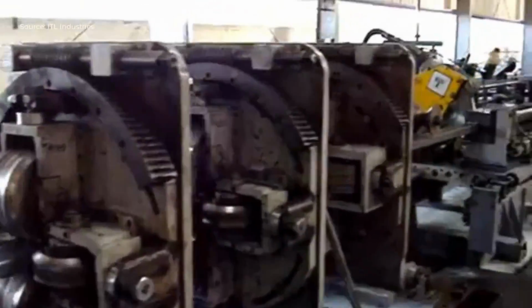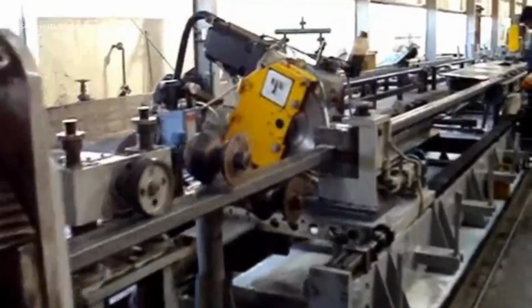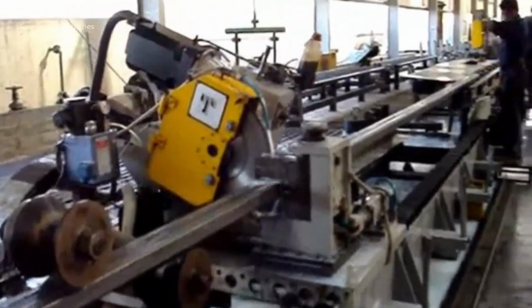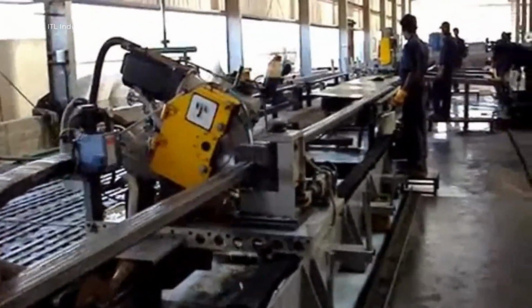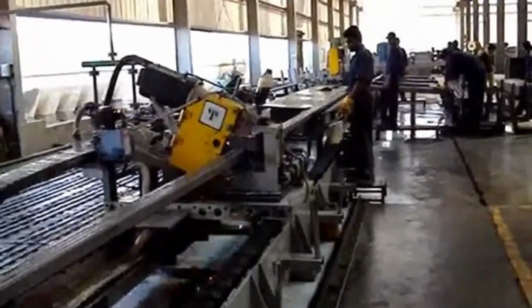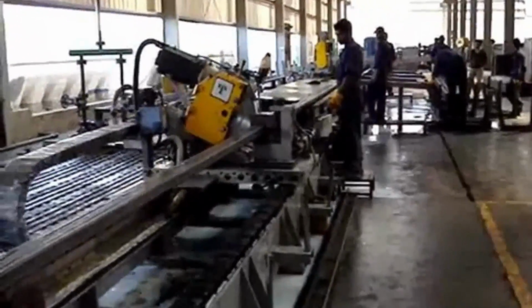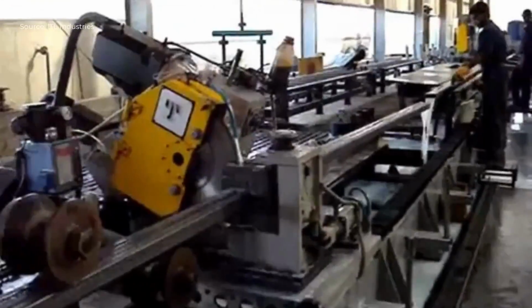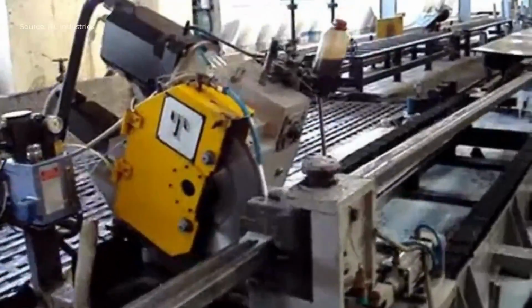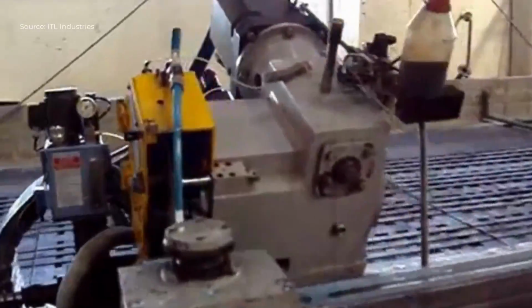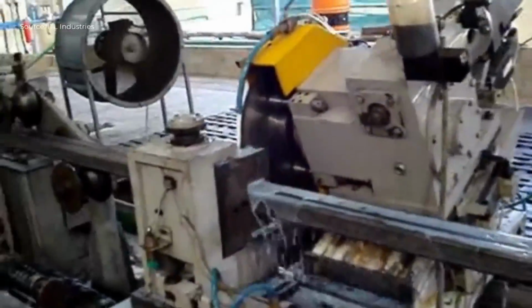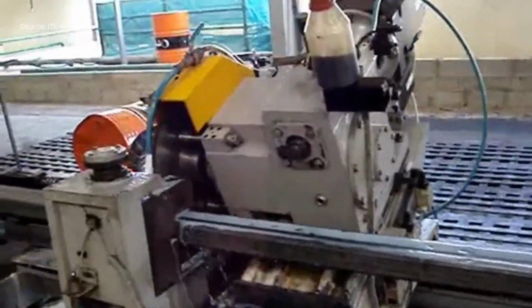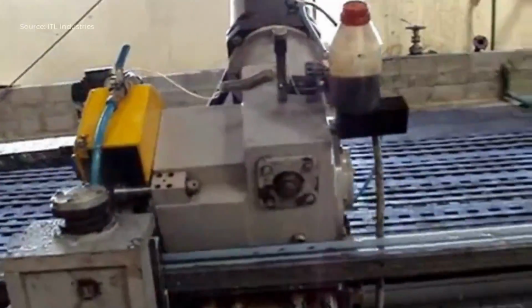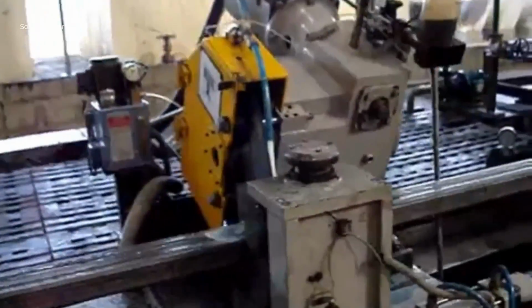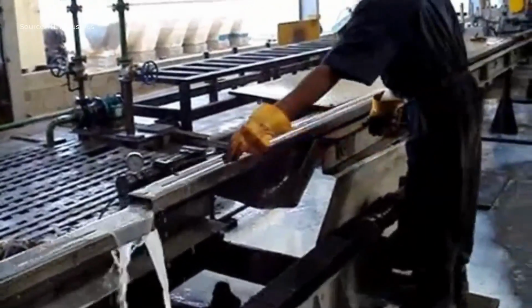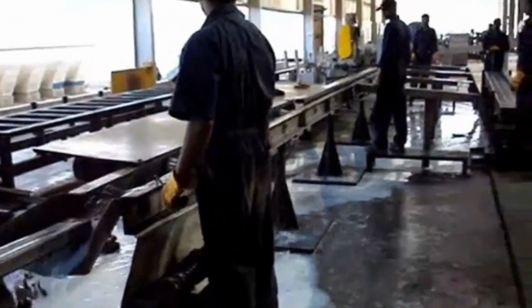In the roll forming stage, the leveled strip is gradually shaped into a square profile using cold roll forming technology. The machine adopts multi-point forming, where each forming stand deforms the strip slightly, changing the contact from line touch to point touch. This reduces surface friction, enhances finish quality, and improves forming stability. The forming stands are adjusted automatically using a PLC control system. The position of rollers adapts based on the input specifications, and only one set of rollers is required to form all tube sizes.